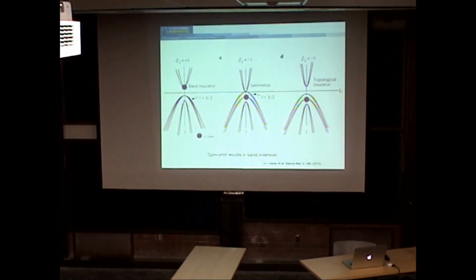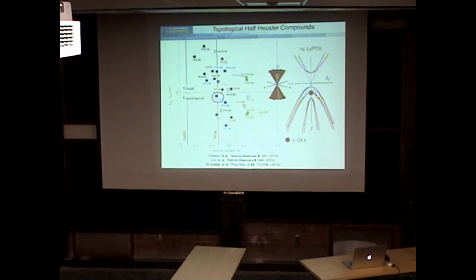One of the ideas here is that if you have a trivial insulator, you'll have the S and P. The P bands will be your valence band, and S will be in your conduction band. But if you get enough spin-orbit coupling, you can invert this and get the S bands below the P's, so that if your material is a topological insulator, you have a gap where you have a P-type conduction band and S-like states down in the valence band. And if that happens, you are supposed to have a surface state on the surface, which is basically this Dirac cone, which should have spin and momentum locked at the surface.